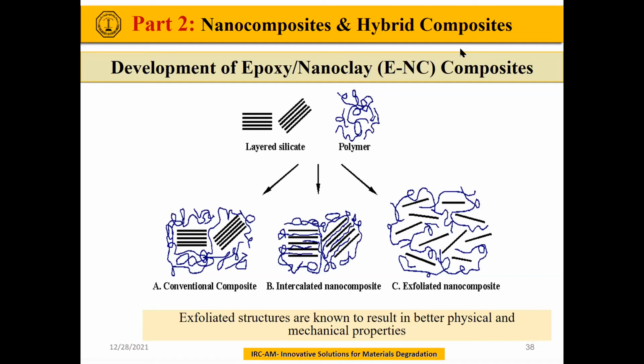These are some XRD spectra that we have obtained for different clay loadings. This is the clay, the I.30P Nanomer clay. As you can see, it exhibits a peak at around 4 degrees.